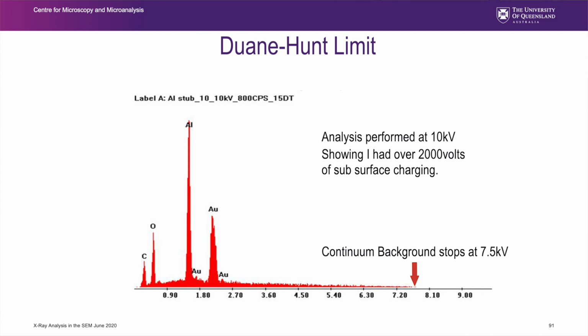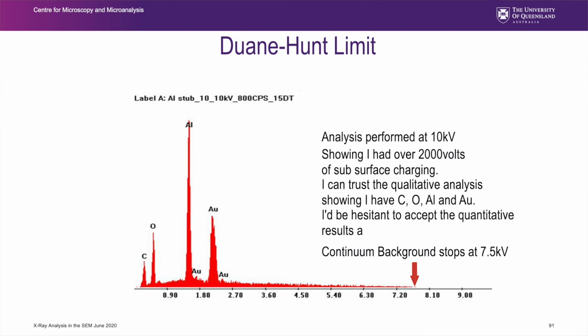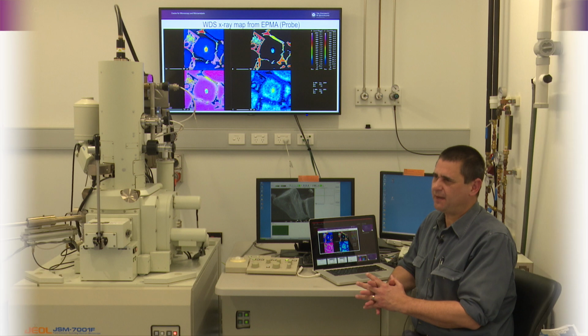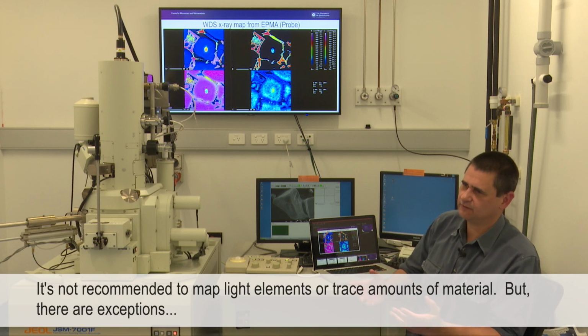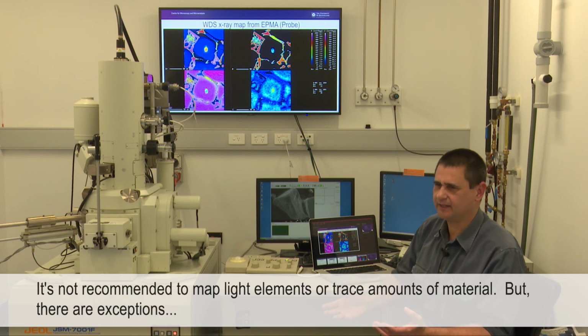I can certainly qualitatively say I got carbon, oxygen, aluminium and gold there. Quantitatively, I'll be hesitant to accept the results, the numbers. Having said that, the gold is a gold coating anyway to make the specimen conductive, so there's a lot of problems quantifying that spectrum anyway. I tend to carbon coat to quantify, and I never quantify carbon. Mapping, it's no good for light elements, it's no good for trace amounts and all this.